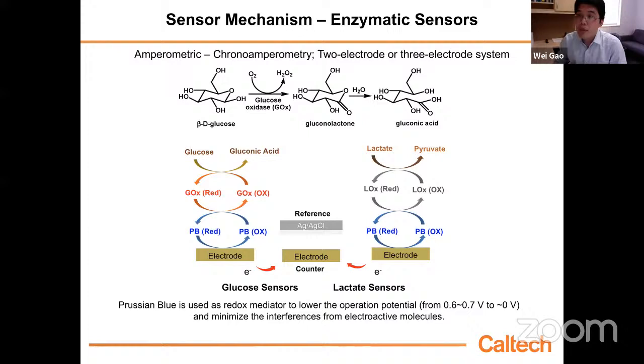Here we are using a generation two glucose sensor. Basically, instead of detecting hydrogen peroxide, we introduce a redox mediator, such as Prussian blue, which can lower the operation voltage of this glucose sensor to around 0 volts. Detecting hydrogen peroxide requires high voltage. If we use only around 0 volts, that could minimize the influence from many electroactive molecules in our body fluid.